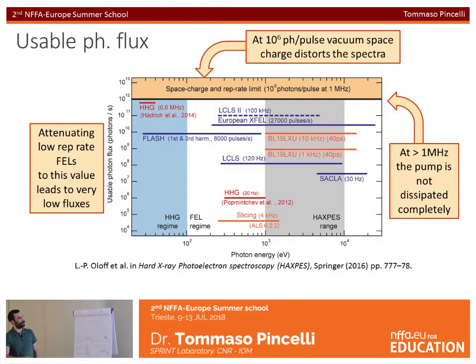On the other hand, you have also a limit on the maximum repetition rate, because if you go too fast, then the sample doesn't have time to recover the equilibrium state. So it's possible to fix somehow a limit of the maximum usable photon flux of the time resolved photoelectron spectroscopy that is in the 10 to the 12 photons per second. Does it ring a bell? Is what we have in our high harmonics generation laboratory. So we are here in the soft X-ray range, and with high repetition rate and just the right amount of photons per pulse. On the other hand, if you need higher photon energies, then you have to realize high repetition rate free electron lasers, which are still underway, or to use synchrotron radiation accepting a reduced time resolution.